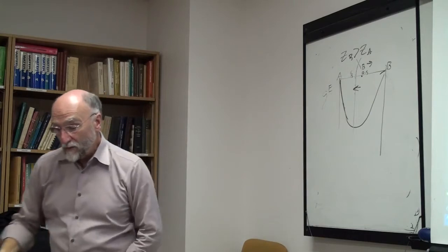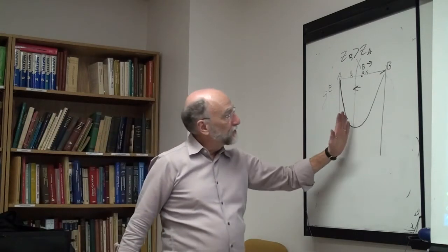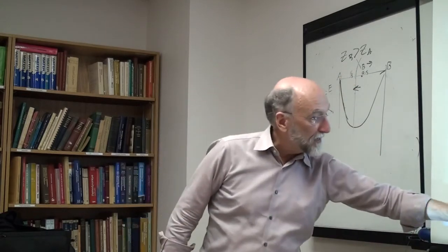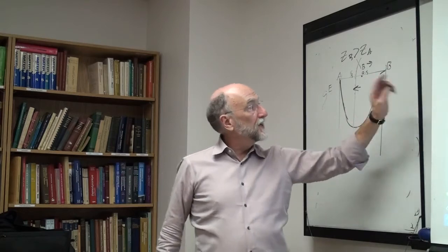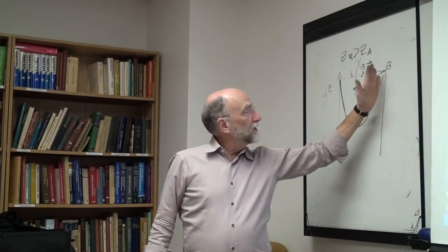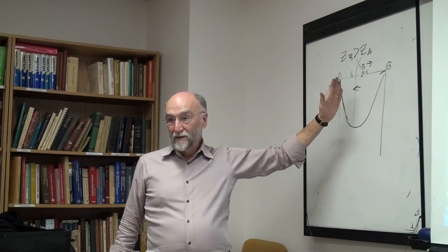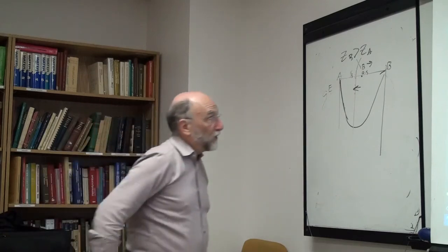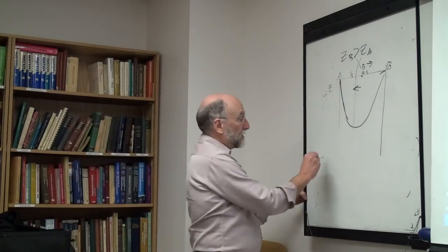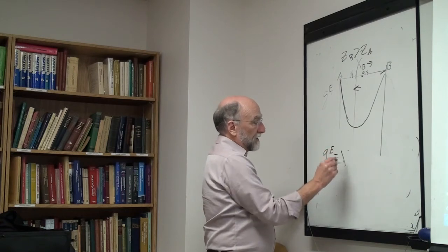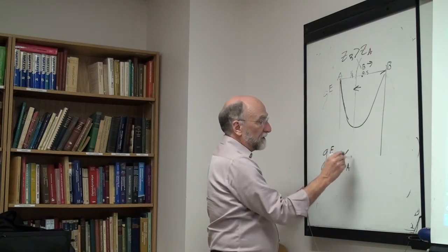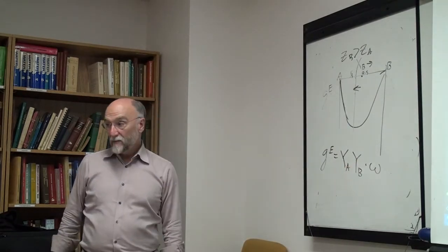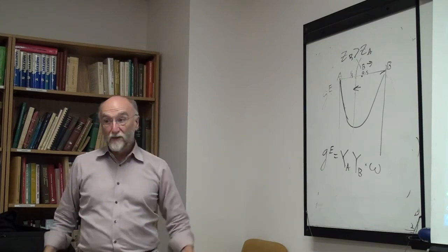Now this is what the quasi-chemical model gives you. In the quasi-chemical model, you can shift the minimum from 50%, even though you keep your omega constant. You can keep the omega constant, and just by making ZB over ZA equal to 2, you have a negative omega, you shift the thing over to the left. Now you can do exactly the same thing in the Bragg-Williams model, in the limit of a small shift, by simply taking GXS is YA YB times omega. That's all I have to do. GXS is YA YB times omega instead of XA XB times omega.